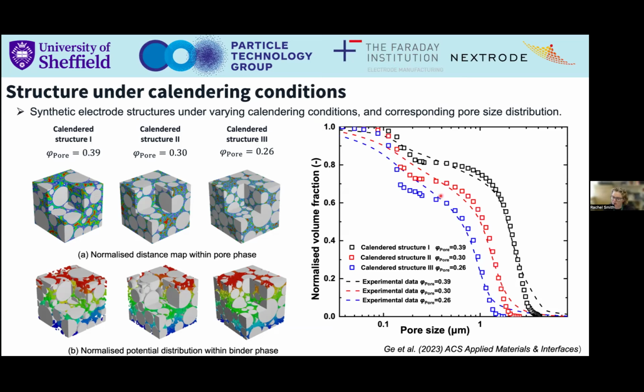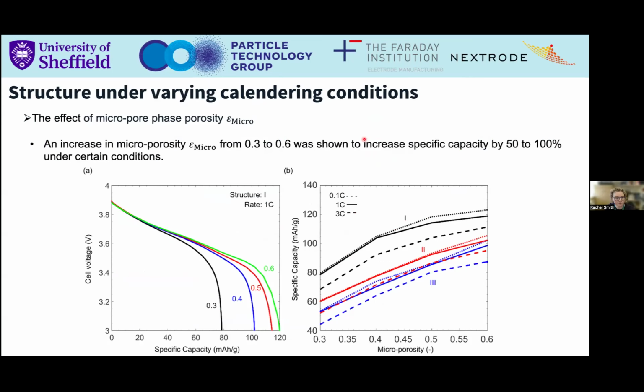But we're not too worried about that, because rather than trying to perfectly replicate experimental data, we're trying to investigate the role of this microporosity. And to be honest, it's not too bad when you think about it. The agreement between the experimental and the simulated data is not too big.